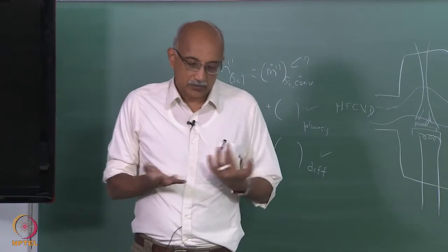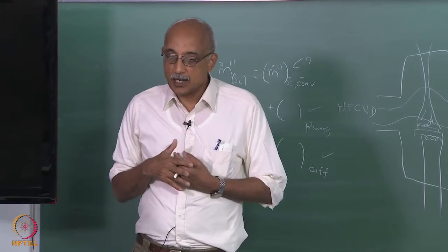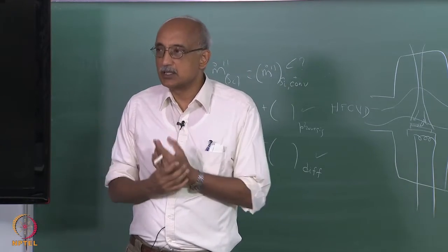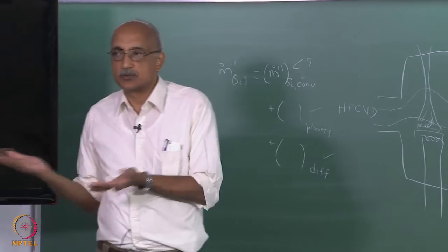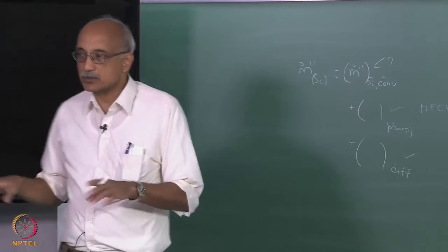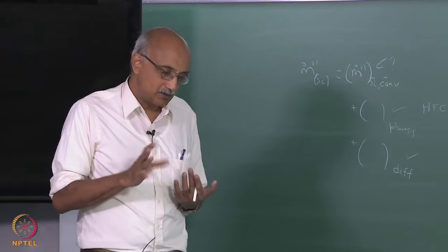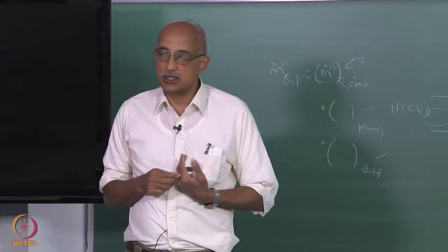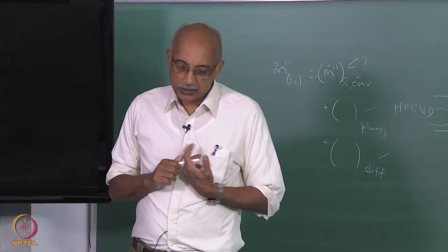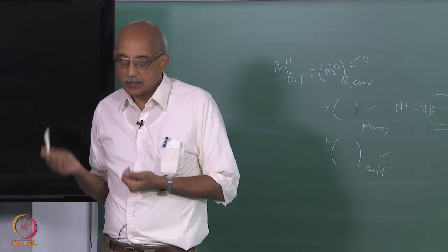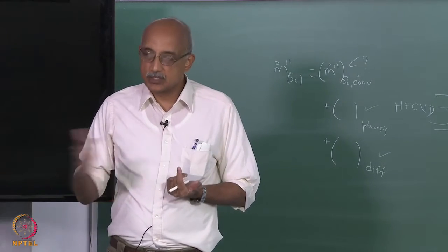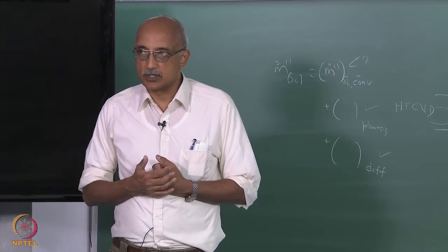In fact, when hot wire CVD was introduced, like I said, back in the 1979 time frame, after a couple of years it completely vanished, because people were experiencing all kinds of problems with it. They were getting huge masses of material, but it was arriving in a way which was not really conducive to use that film later in the process. So, for about 4 years people said, let's not use this process, but others started working on it and tried to iron out some of the problems associated with hot wire CVD, and have now brought it to a stage where it is again a commercially viable process. But at the same time, it is something that you have to use with caution, and it does require more controls on both uniformity of temperature and uniformity of flow compared to the more conventional horizontal flow CVD reactors or stagnation flow CVD reactors.